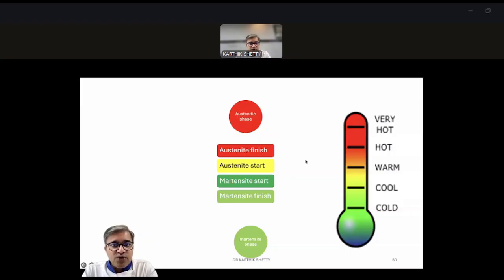And as the temperature lowers completely at one point, whether it is 37 degrees, 30 degrees, or 28 degrees, depending on what the manufacturer has decided, it will become martensitic finish. So if martensitic finish is 25 degrees, below 25 it is fully martensitic. And if the austenitic finish is 50 degrees, above 50 degrees it is fully austenitic. So above 50 it is very stiff, below 25 it is very flexible. This is assuming what the manufacturer has done. So with this said, we now know what the austenitic phase and martensitic phase are, and we will proceed because some parts of this will have a bearing on what we are going to speak next.